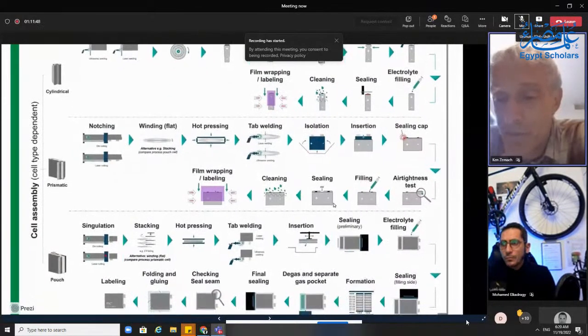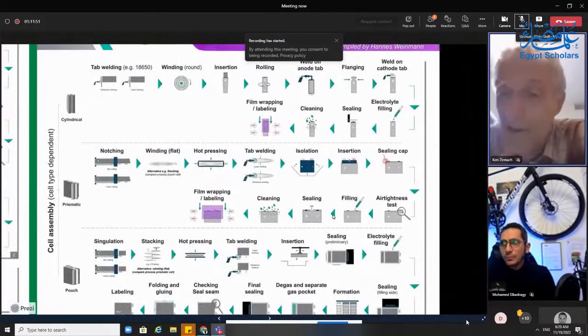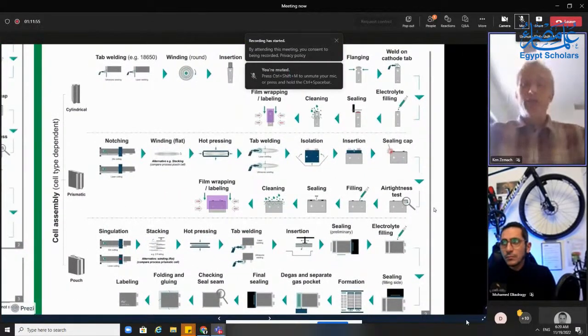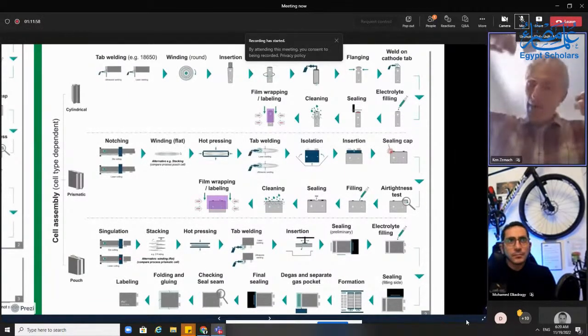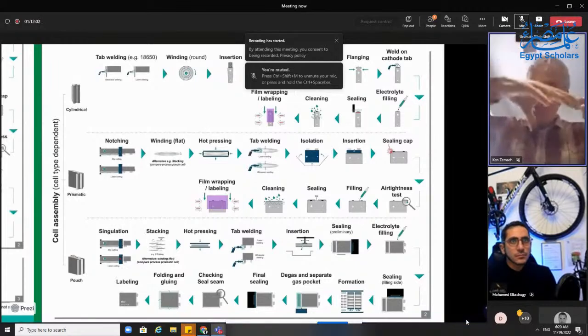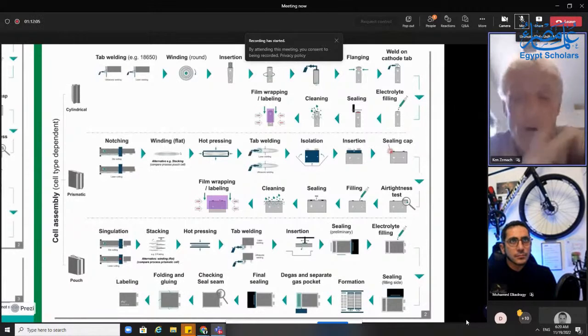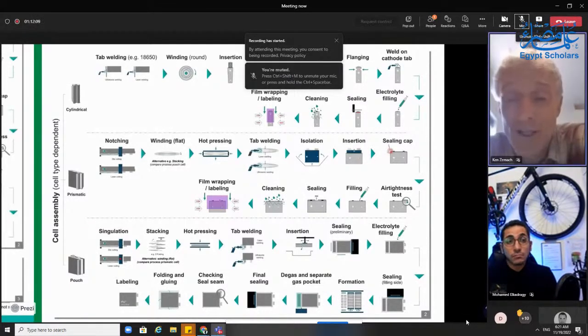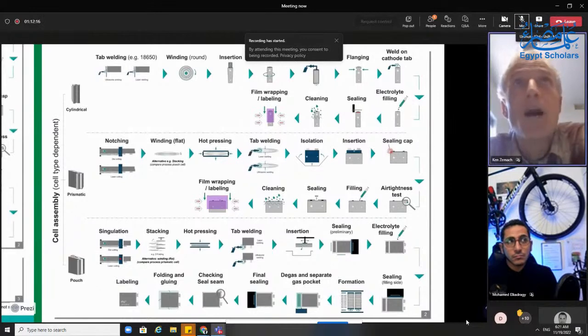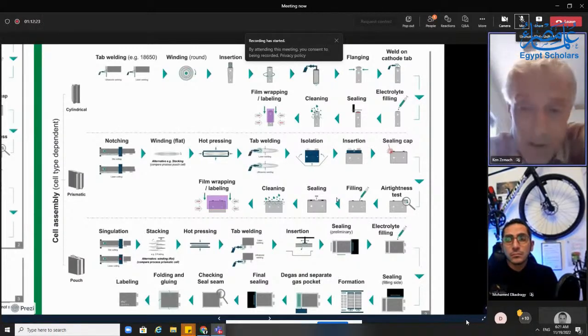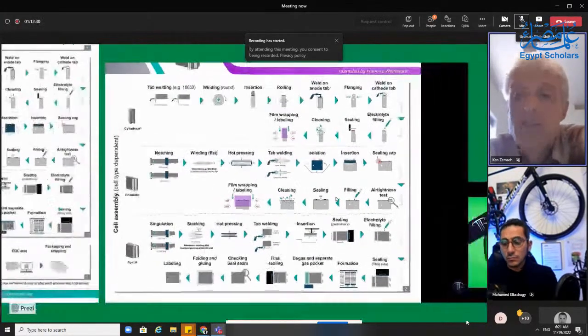This is not like soaking water into a sponge, which, by the way, also takes time. But imagine that you have a giant sponge in a package and you put some water in one part. It's going to take time to soak through. And until it soaks through, you have 2 problems. One, you can't get enough electrolyte in, because you need to get in a certain amount. Sometimes electrolyte filling can take 30 minutes. You pull a vacuum and then you put pressure, and you pull a vacuum and you put pressure, and you pull a vacuum and you put pressure. But remember, electrolyte is flammable, it's toxic, it's hazardous, and it can't be exposed to water. So all of this is done in a dry room.